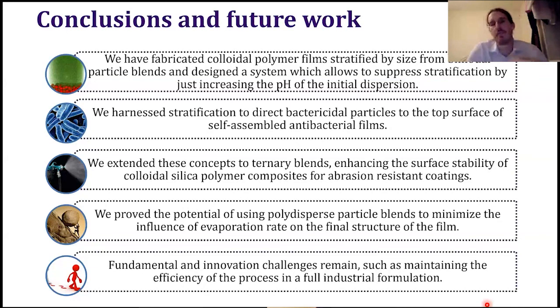Then the next thing we've been doing is harnessing this process to develop two different applications successfully. The first of them has been fabricating antibacterial films. This way we are able to optimize the amount of bactericidal or antibacterial agent that goes to the surface. And in principle, you could also reduce how much you put into your coating and reduce cost. Then we have also developed abrasion-resistant coatings, so that you enhance the surface stability of coatings, which might be good also. There are also some concerns about the toxicity of nanoparticles, etc. So if we use this concept, we will also reduce how many of these are released